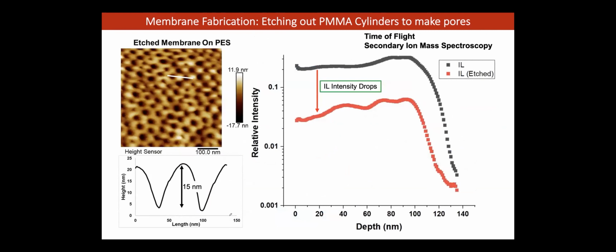But we do need other techniques, is my point here. For example, how do we know we removed ionic liquid? And so here we do time of flight SIMS, and this is very useful. And you can see that the chemical signal from ionic liquid drops from the black curve to the red curve in the etched membrane compared to the unetched membrane. And if you do GISAXS alone, you would see a big intensity increase because air polymer contrast is much higher than ionic liquid polymer contrast in the pores. However, you can't assume that it's the ionic liquid that went away. Could it be something else? So there's a clear chemical signature.